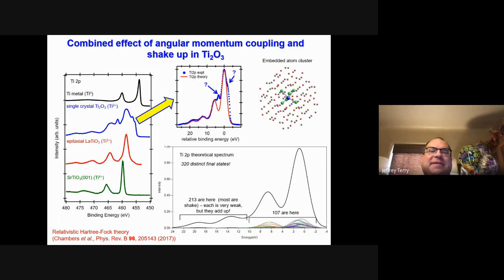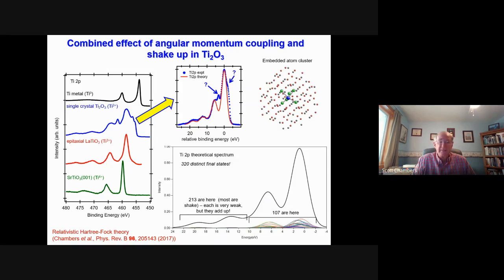Yeah, what almost surprises me more is not these somewhat unusual cases, but the fact that there aren't more of them, and that is remarkably fortunate for most of the people doing XPS. Yes, indeed. This is probably the most bizarre. This is one of the most extreme cases I've ever seen in terms of those two spectra in the middle, the blue one and the red one, being so different for nominally the same valence. That one takes the cake.